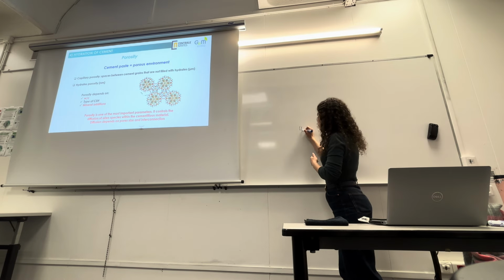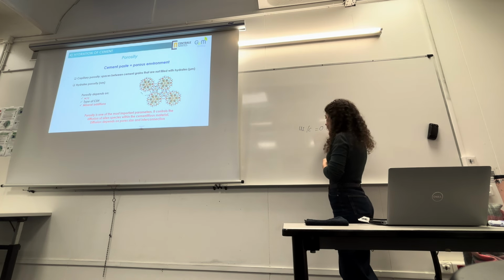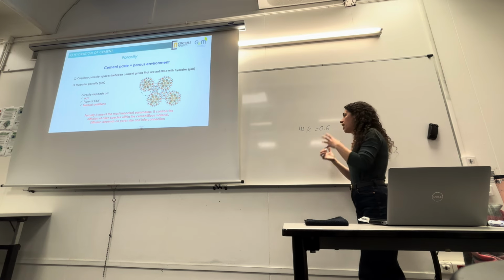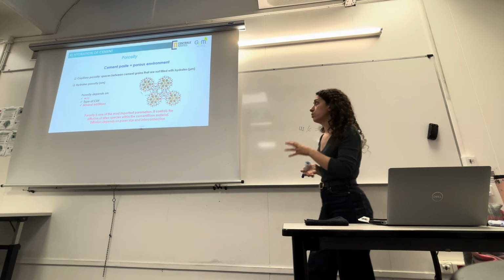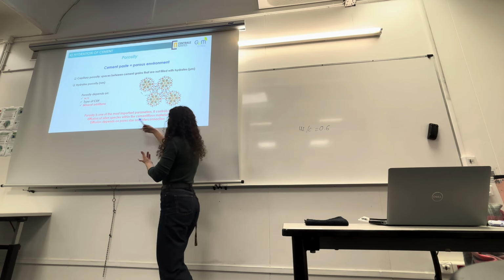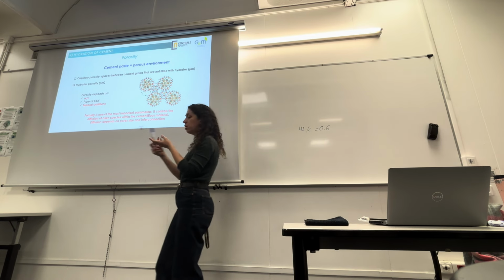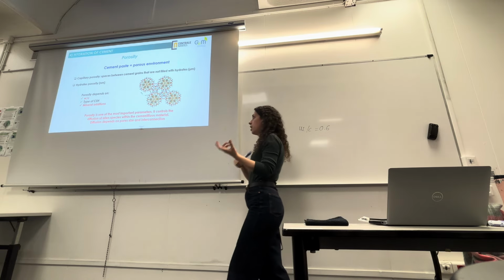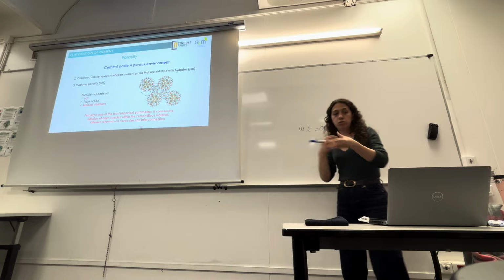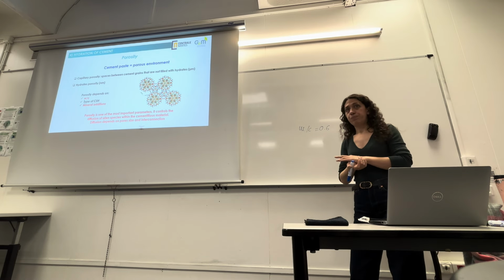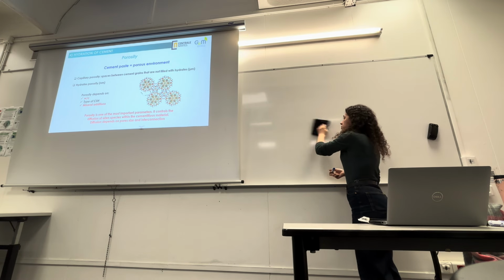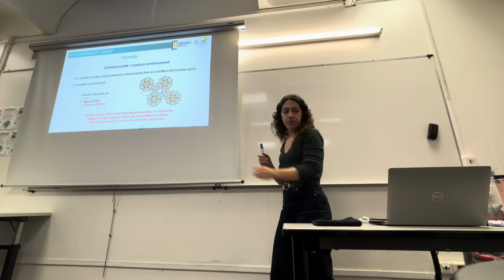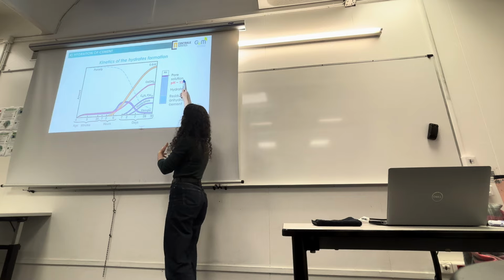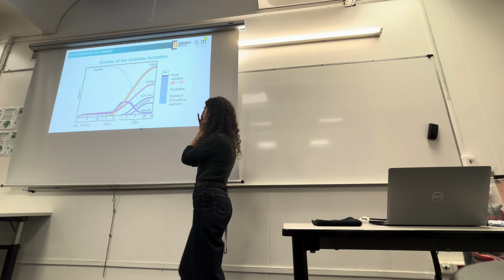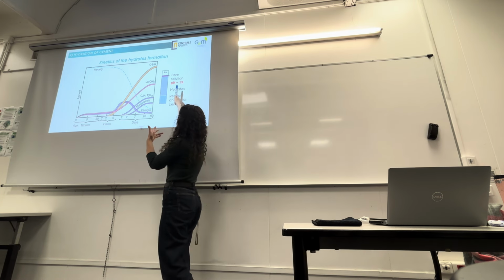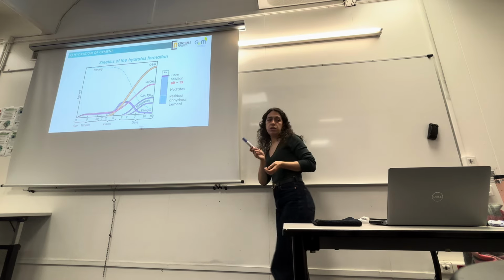If you have a water-cement ratio of 0.6, that's very high. That means you have very porous materials. And if your material is porous, you will have continuous diffusion of ion species, of chlorides, sulfates from the environment inside your cementitious materials. But if you have porous materials, you will also have less mechanical strength. So the specific amount of different elements that compose the cement paste depends on the water-cement ratio.